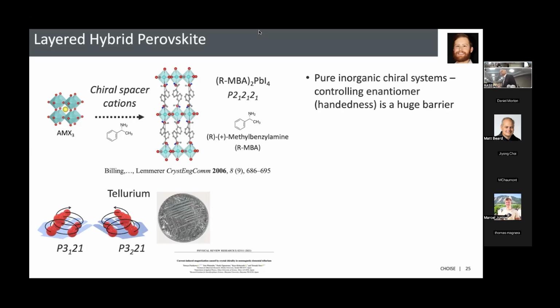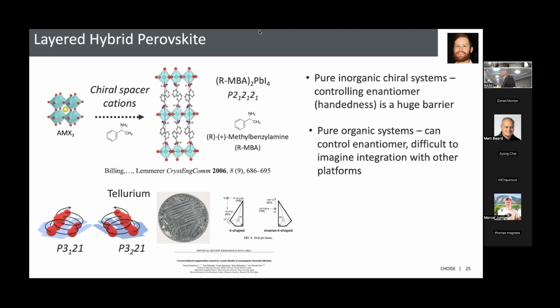Tellurium is the sort of prototypical example. It's a chiral metal, or a chiral semiconductor. But when you grow it, you don't know whether you get this version or that version. And the way some people try to figure this out is they etch the surface, and if they get this etch pattern, it means it's right, and this one it's left. And so then they can study their properties. But to actually separate them is quite hard. I should note there's a huge research effort in trying to grow tellurium with only one handedness. So probably there'll be progress on that.